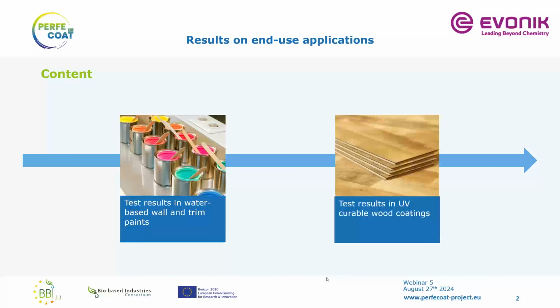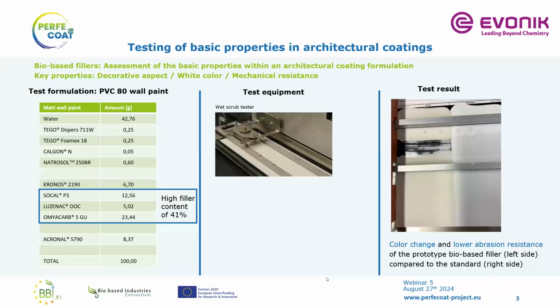And in a second time, we will have Roland from Remmers, who will describe the test result for the UV curable wood coating. So I will start with some first data we have generated in architectural coating by testing some bio-based fillers. You can see on the left side, description of the guide formulation. So typically those formulation, what you have on your wall in a room, it's a PVC 80. It means it's a formulation that contains quite a lot of pigment and fillers relative to the amount of binders. So it gives it a matte finish.